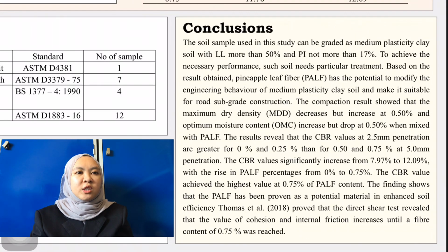The findings show that the pineapple leaf fiber has been proved to be a potential material in enhancing soil efficiency, which is proved by the direct shear test that revealed that the value of cohesion and internal friction increased until a fiber content of 0.75% was reached.